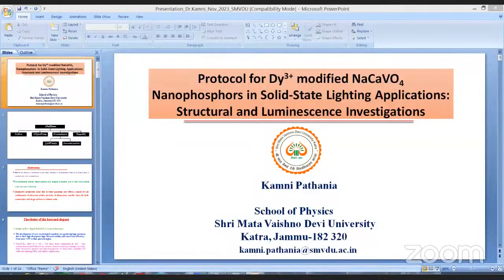amount of gases. Then we have cooled down the alumina crucibles to room temperature and transferred the powder into a mortar and pestle again for grinding. After this, the annealing process is done at about 880 degrees Celsius in order to enhance the crystallinity of the sample. The prepared powders are finally preserved for the characterization.